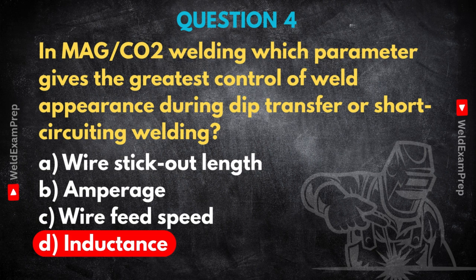Yeah, that happens. If the inductance is too low, the arc gets really harsh, very aggressive. You might hear it described as crackly or stiff. The biggest visual cue for an inspector is excessive spatter, like you said, and not just a few bits, but everywhere, lots of it. The weld bead itself might look quite irregular, almost ropey, not smooth ripples, but coarse, uneven ones. You might also see inconsistent wetting at the edges, less smooth fusion.